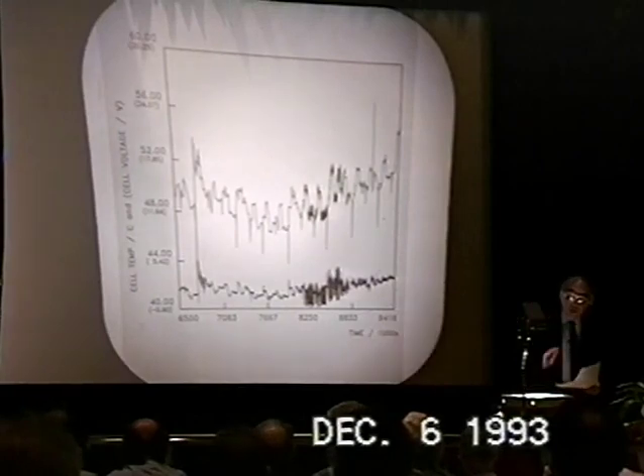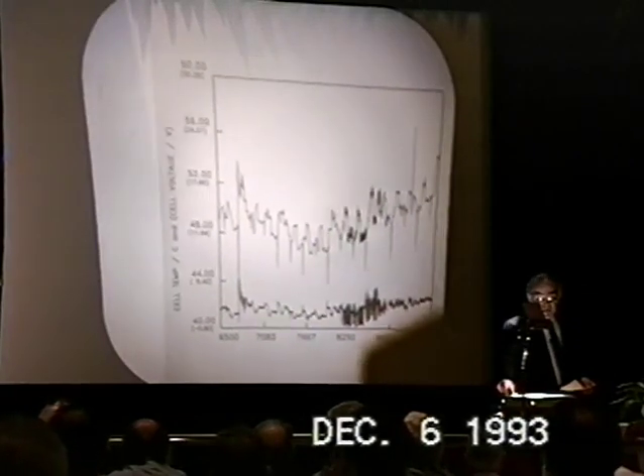Now, apart from these oscillations which you see at that transition point, let me show this to you again, there are no oscillations, especially there are no oscillations in the cell potential. Stein and I do not follow the electronic mail, but from time to time, people make various statements that there are oscillations in the cell potential and we do not take them into account. This, I must tell you, is complete nonsense. Since we carry out a very large number of experiments, we normally only measure our cell potential at rather long intervals, about 300 seconds. But we do monitor all the oscillations.